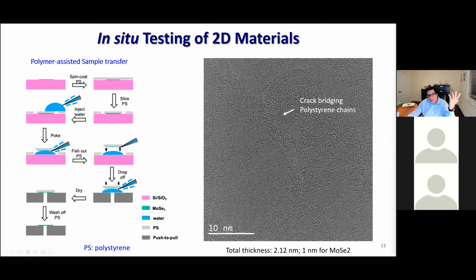the community for making field effect transistors or other type of nano devices, which consist in starting with a substrate that is typically silicon with a layer of silicon oxide, and the monolayers that have been grown by chemical vapor deposition. So you have many of these flakes in different regions of the wafer, and you can then spin coat a polymer and then cut a region containing the flake. The flakes typically are 5 to 10 microns, so this is doable.